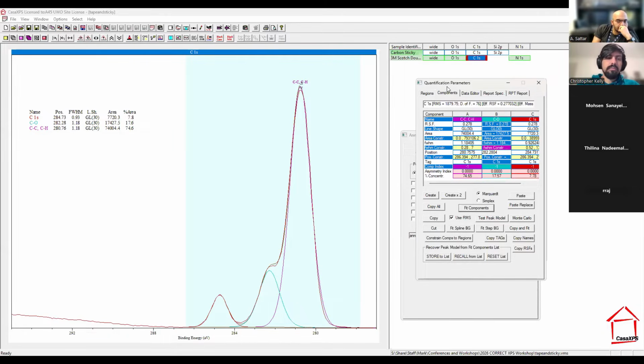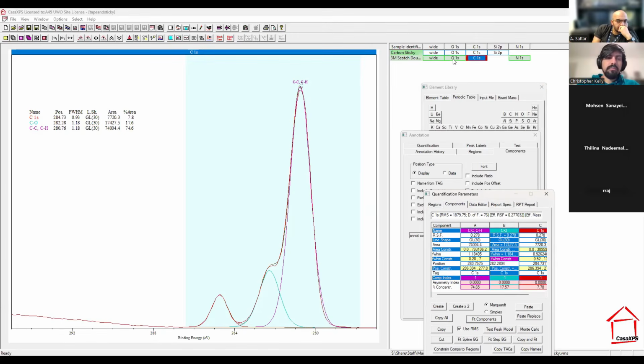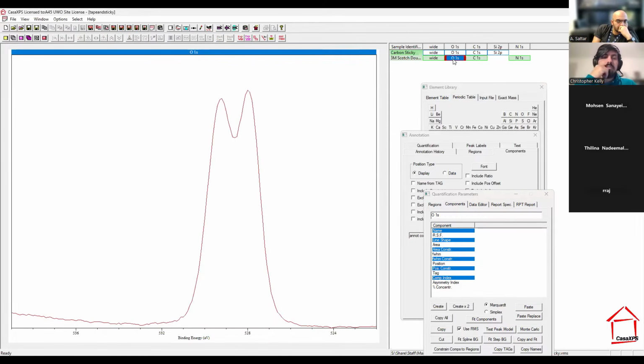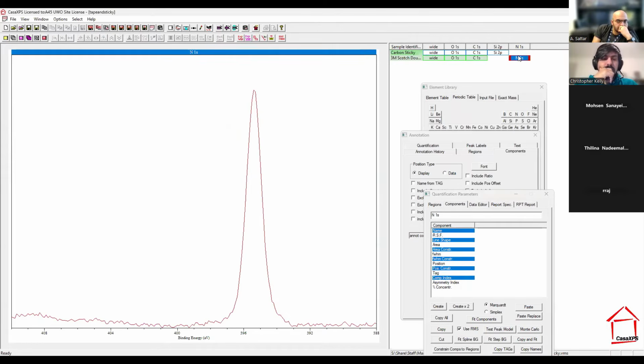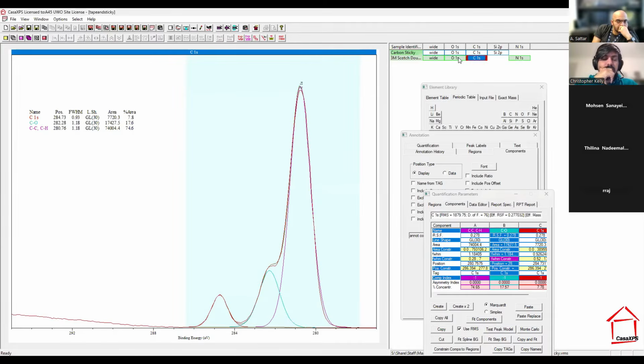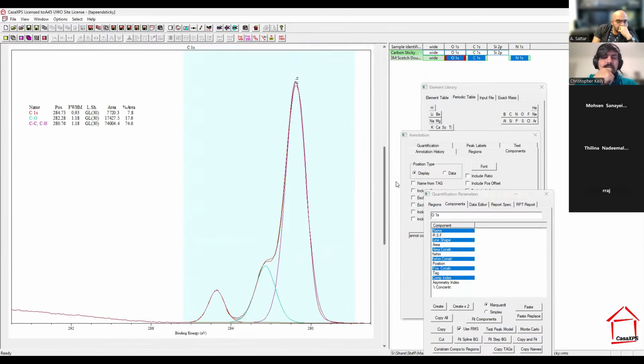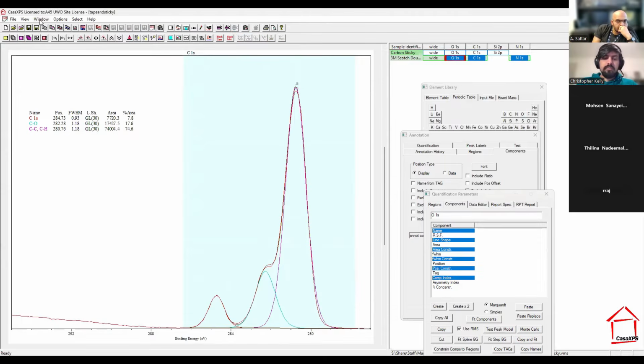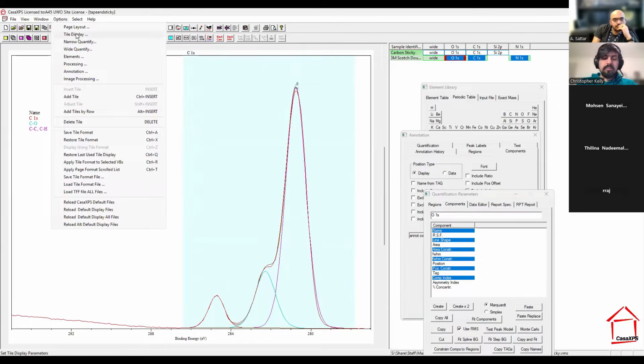But we also want to shift the peaks down for those elements that we also took at the same time. So the oxygen peak is going to be shifted down, the nitrogen peak is going to be shifted down. And so what we're going to do is select all these peaks, go down, and go to processing.